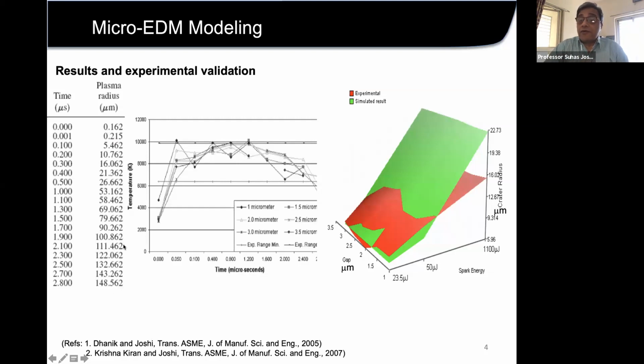Later on, these were calculated values, but later on, Professor Kunieda from Japan has actually used these calculated values to verify his experimental values. He was able to generate a single spark and actually measure the size of the plasma column. And here we found that our model and the experiments agree well when the total spark energies are lower, but when the spark energies are very high, then our model was giving larger results over the experimental results.